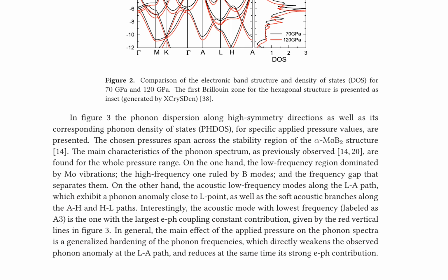Phonon dispersion and density of states for specific pressures highlight the low-frequency region dominated by Mo vibrations, the high-frequency region by B modes, and the frequency gap between them. The main effect of pressure is a generalized hardening of phonon frequencies, affecting the phonon anomaly at the LA path and reducing its strength.